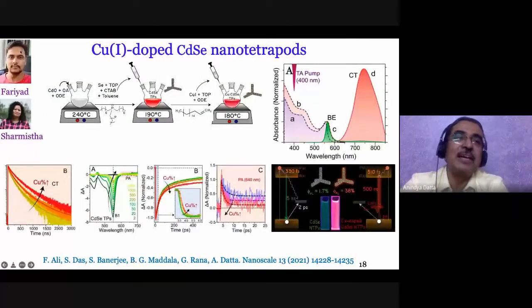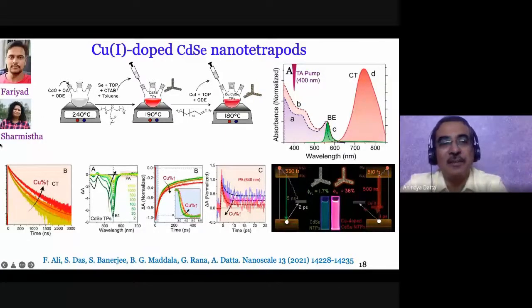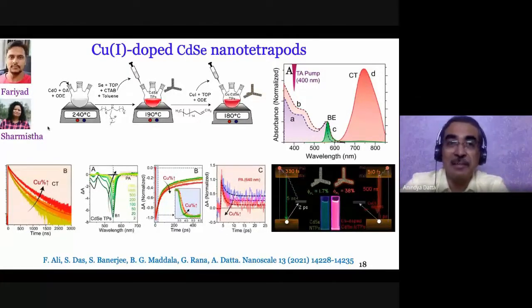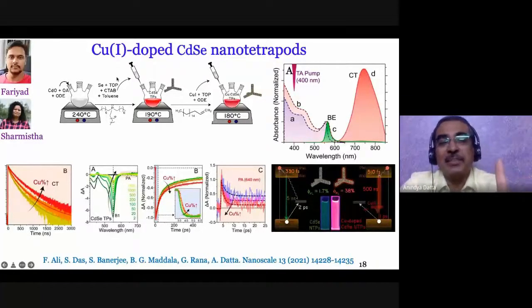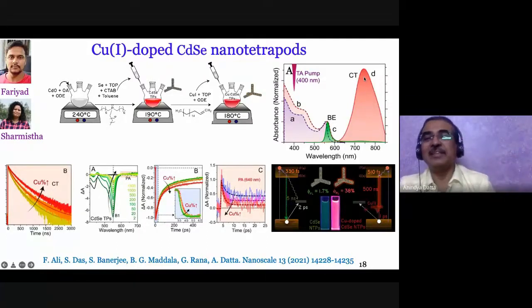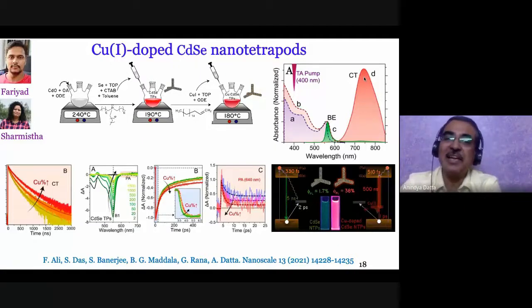It was started by Sucheta, completed by Fariyad, another PhD student who will hopefully graduate this year, with help from Sharmishta. What they did is that they learned how to dope these cadmium selenide nanotetrapods with copper. And please note, this is copper 1, Cu plus, not Cu2 plus. Upon successful doping by copper 1, we could get this redshifted, relatively intense band. Quantum yield here is 30% compared to something like 1.7% or 6% best case scenario that you observed in undoped tetrapods.